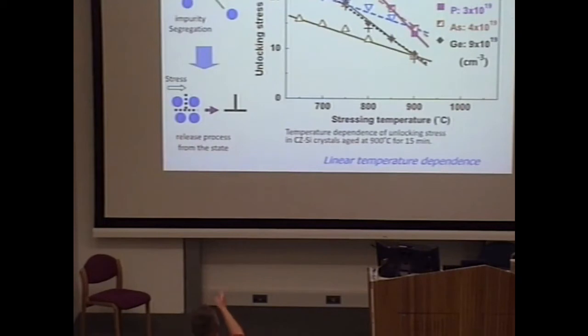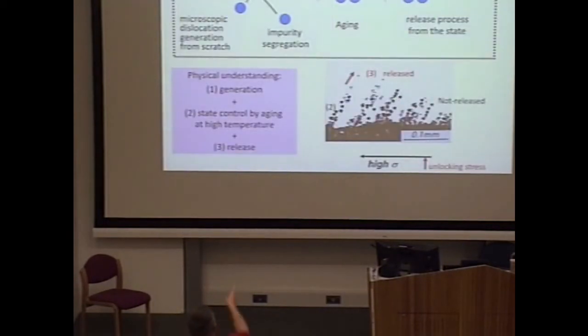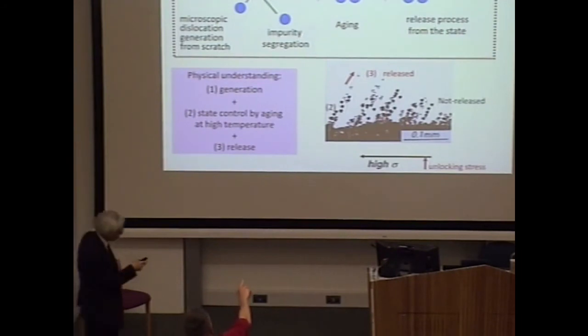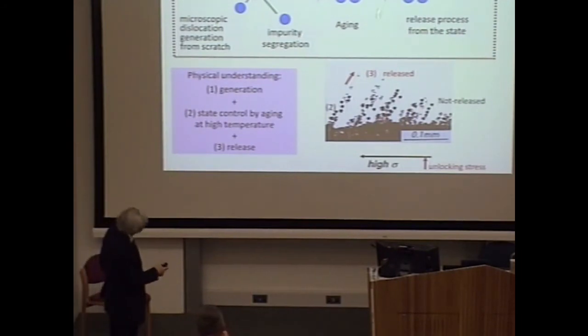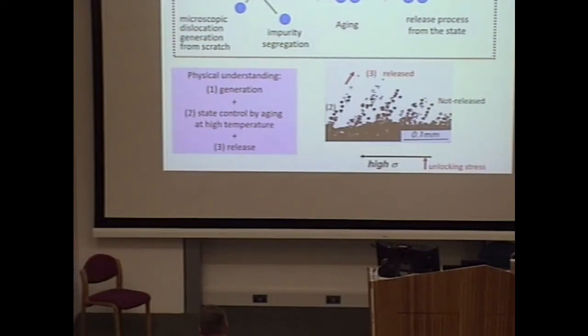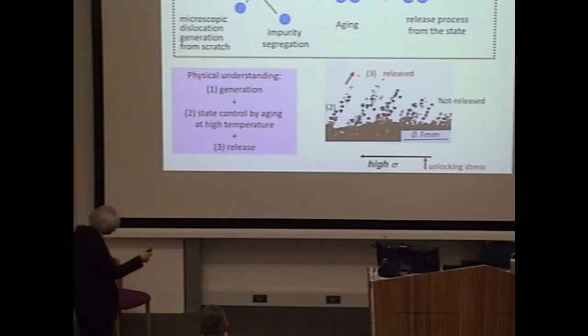How were those dislocations made visible? This is etching. Etching, okay. So by introducing the dislocation, and then etched. Okay. Because the largest etch pit has two etchings, two times etchings. But the small one is only one etching.